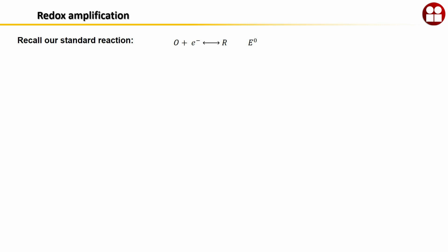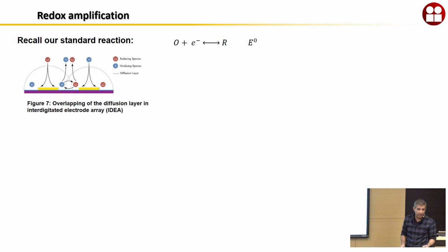So again, we talked about this. How can we amplify the signal? Instead of one electrode, we can have 2 electrodes sitting next to each other. This is a demonstration of a very thin layer of gold electrodes. This is about 20 to 50 nanometer of gold electrode on a substrate. You can see the bulk is diffusing to the surface of the electrodes, forming the reaction, cycling between the 2 electrodes, and going back to the bulk solution, right?